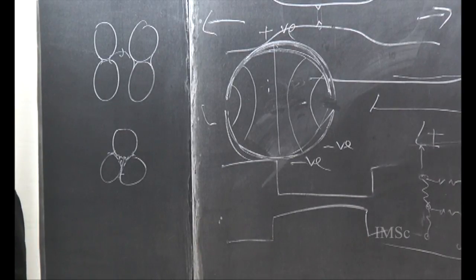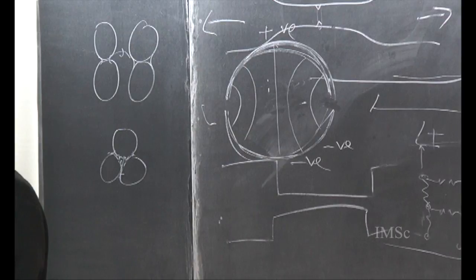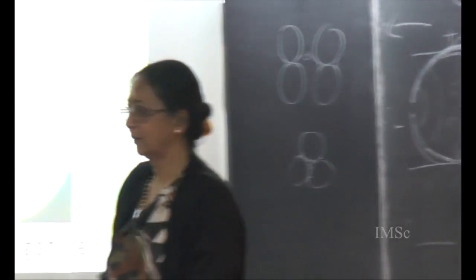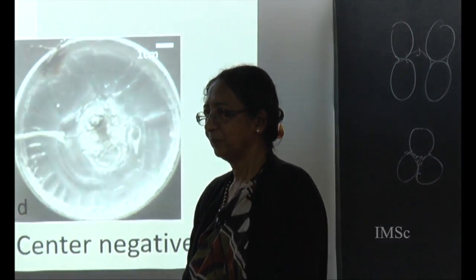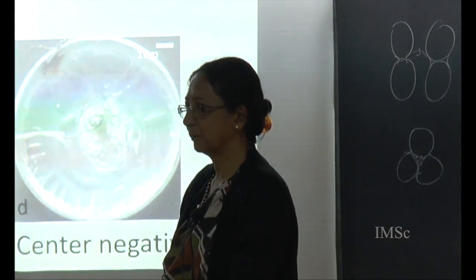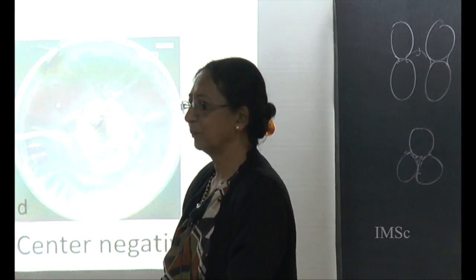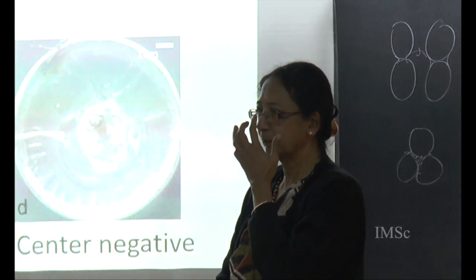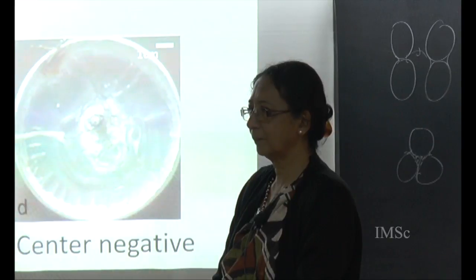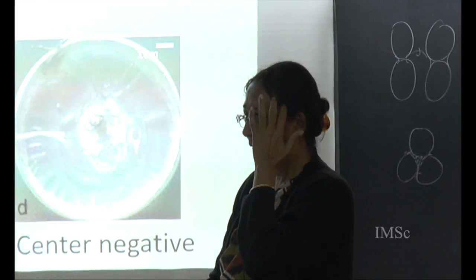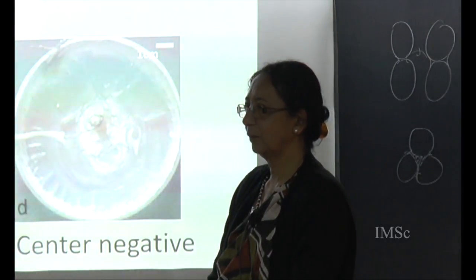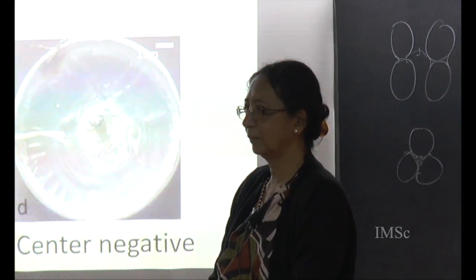Okay, thank you. Yes? You were comparing your ripples to the ripples that can be seen in Perspex fracture. I remember in mode 1 fracture in PMMA, when you have a fragile interface, the type of experiment that Daniel Bonamy was showing, some that were done in Oslo and studied there, very typically there are lines which correspond to the crack front that remain behind the crack path, and these white lines appear when the front is pinned. And when the front passes fast, there's no line. So you can read the history of the crack front motion on the white lines you have.